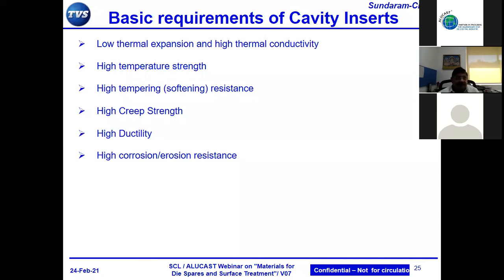But over a period of time, with all this cyclic temperatures up and down, the creep strength of the material should be very high and very good. So you have a thermal stability in the die. This will actually help in getting good parts with good dimensional accuracy. At the same time, any kind of distortion in the die can be avoided. Over a period of time, you see that dies tend to flash. So it actually talks in terms of a poor creep strength of the material which has gone into it.